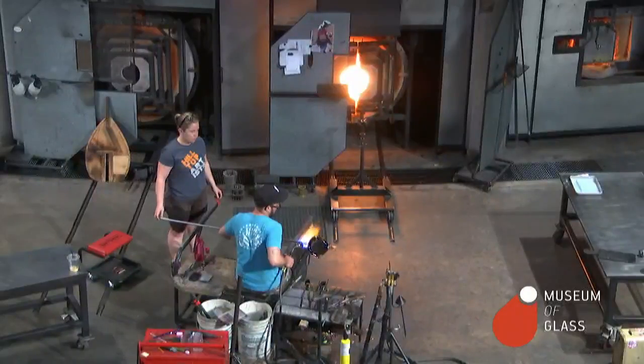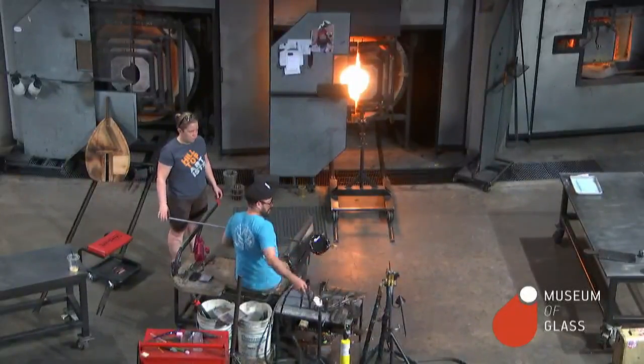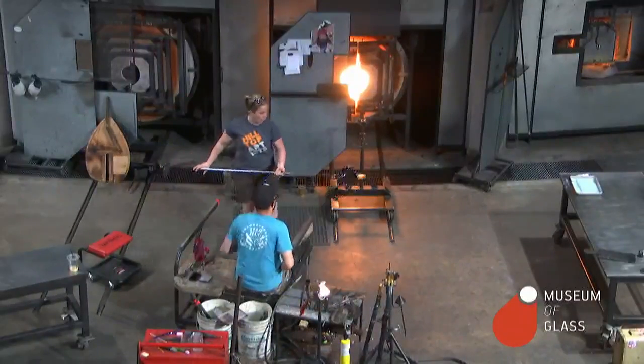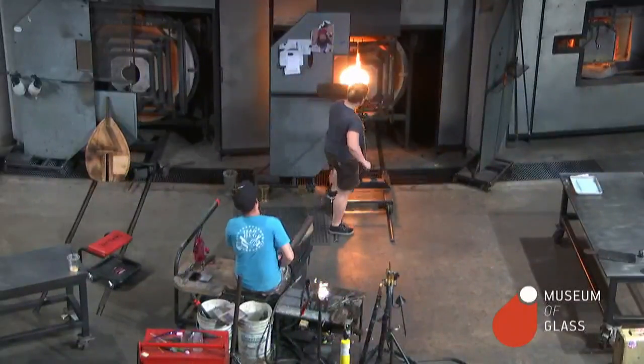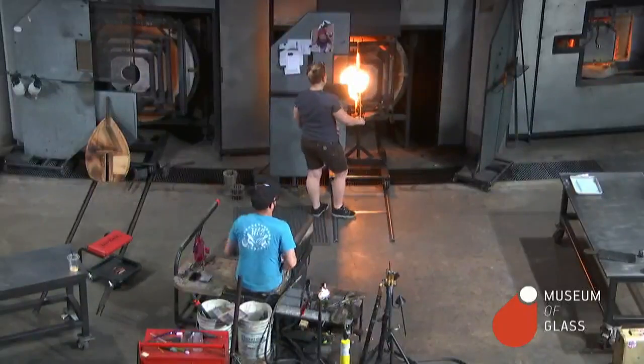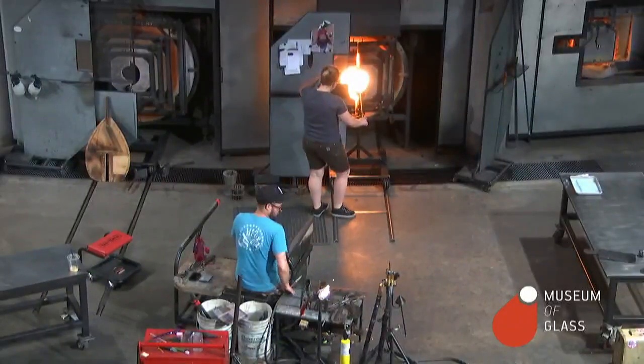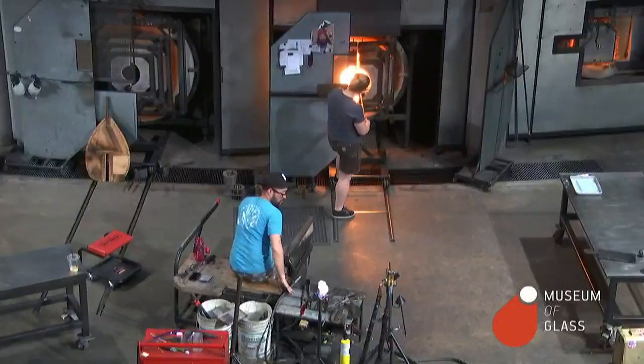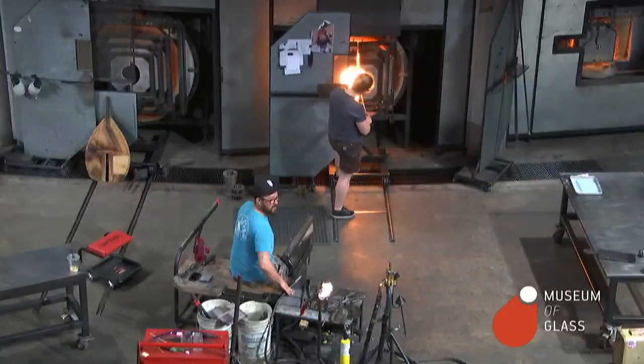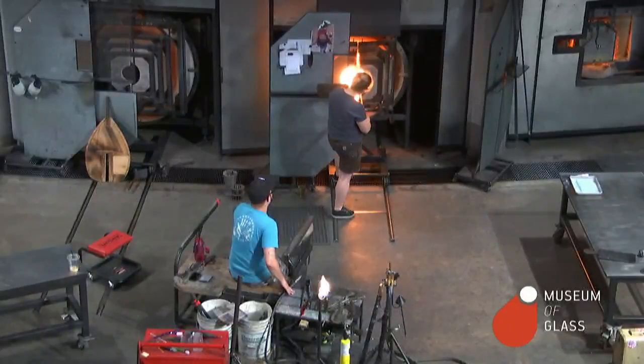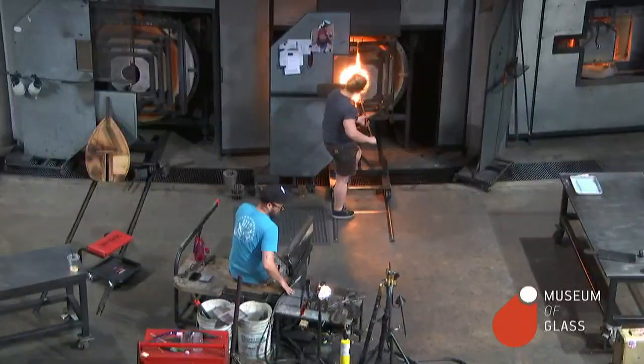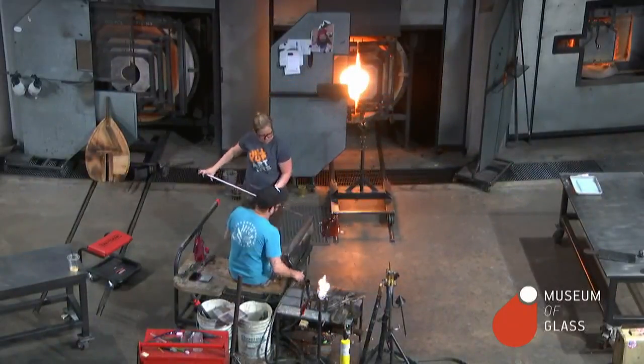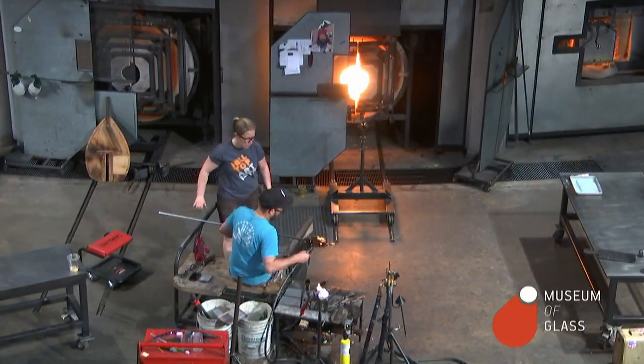So we've used certain glasses that are called reducing glasses. And when we expose them to a very gassy flame, you can see the flame licking out of the round oven. It brings the metallic content of the glass to the surface. It's called reducing. And we'll get a little bit of a metallic sheen.